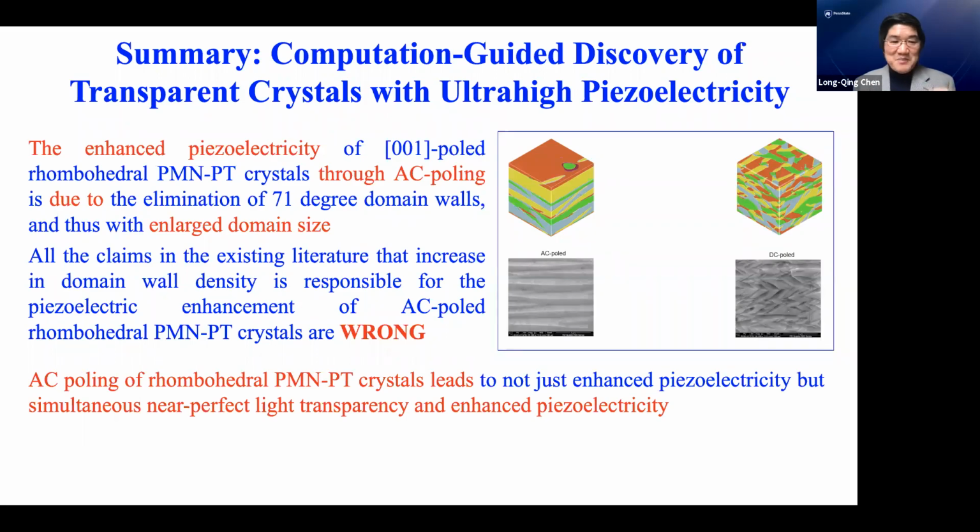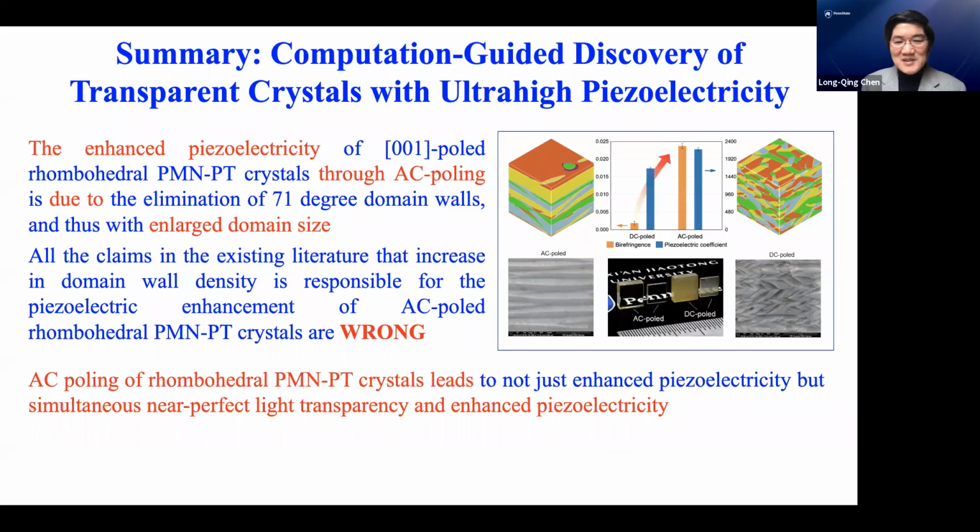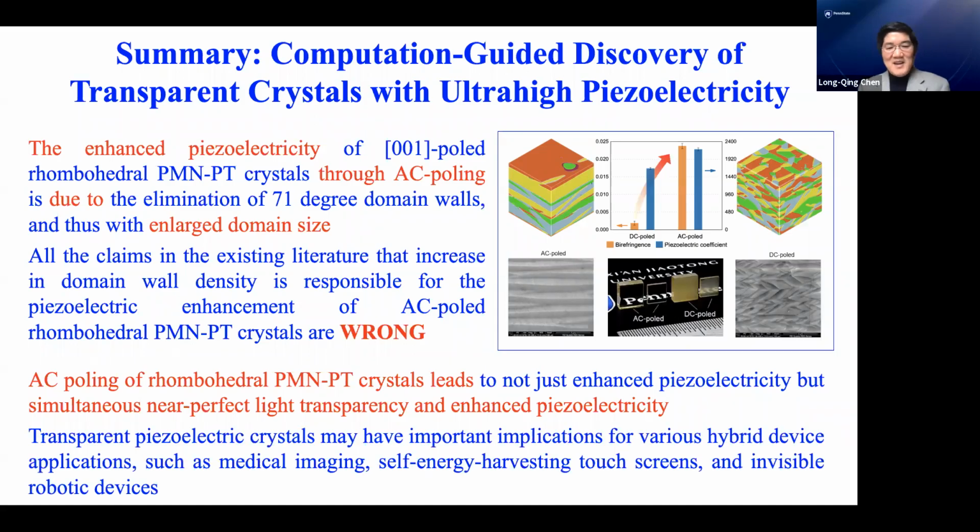Also, we show that the poling, in this case AC poling, not only enhances the piezoelectricity, but actually leads to nearly perfect light transparency of the crystal. So we actually achieve both enhanced piezoelectricity and nearly perfect light transparency. As I mentioned, we can imagine a lot of different applications for these transparent piezoelectric crystals with very high piezoelectricity.